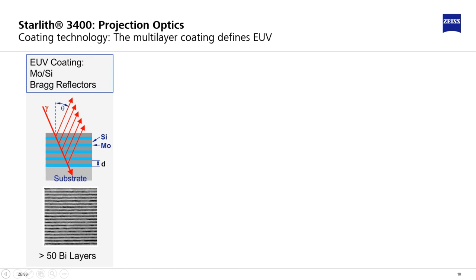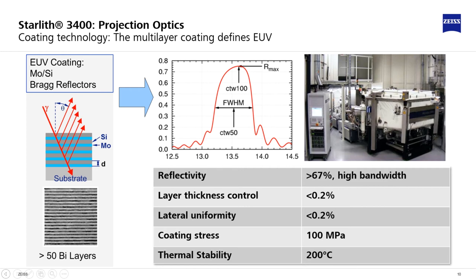Together, they form a so-called Bragg reflector. The reflectance curve over wavelength of such a coating is usually roughly a bell-shaped curve. For high bandwidth, the maximum reflectivity is around 67%.